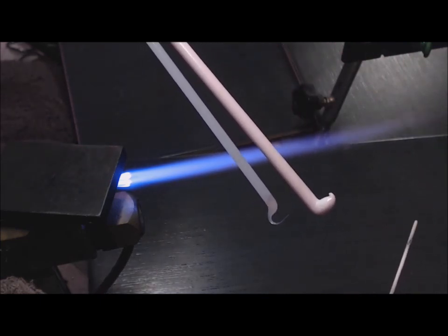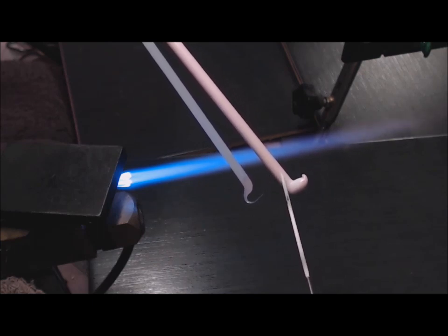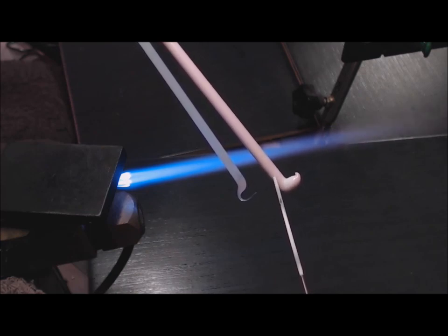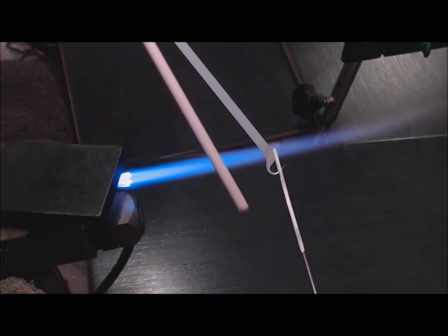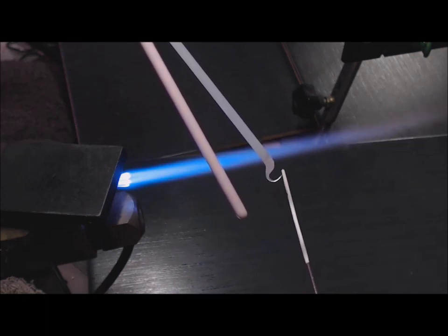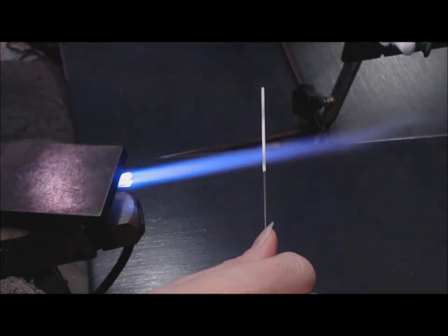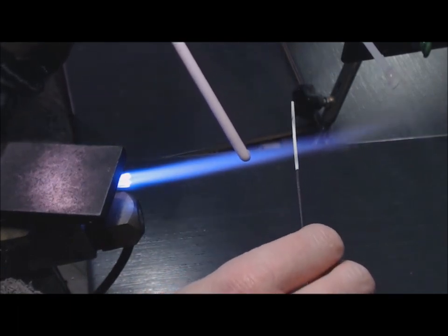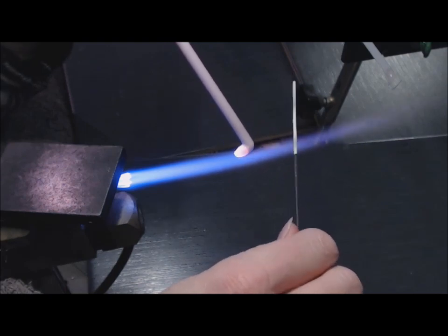Okay, here. You can see that this pink rod, which is a standard Effetre pink, has two colors. Here it's almost white, and here on the rod it's pink. This one here is the opalino rod, pink opalino, and the rod came white when I purchased it, and I've already struck the tip here, so I can see a little bit of pink. So if you're wondering why your pink glass gives you white beads, it's very probably because it is a striking color and you haven't struck it.